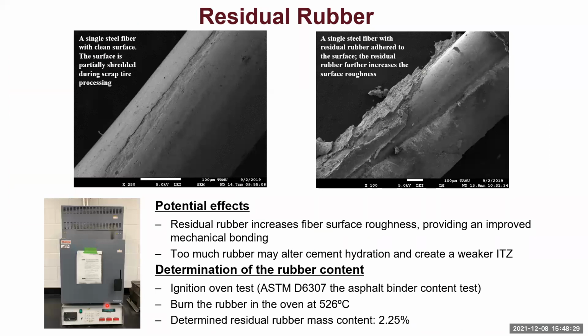So one of the unique properties of the recycled steel fiber is that we have a lot of residual rubber adhered to the fiber surface. As you can see from the SEM image we took, you can see a rubber layer on the surface. So we think the rubber can have some potential effects on concrete properties.